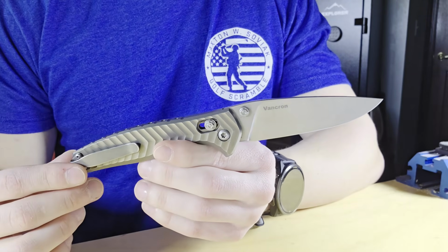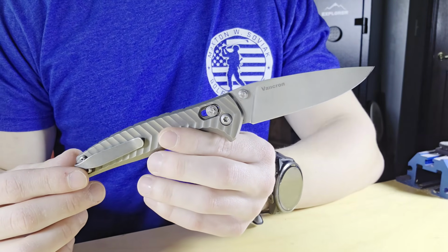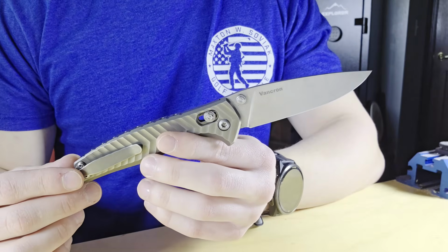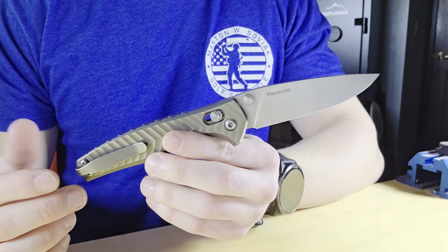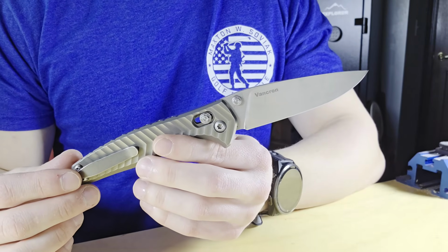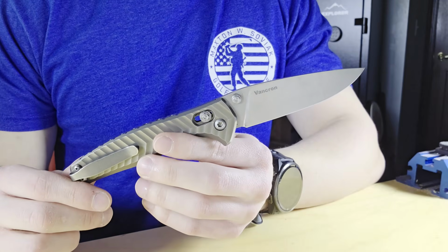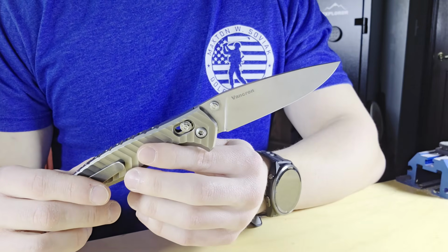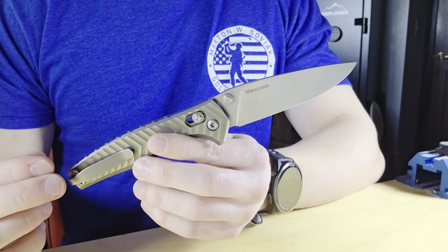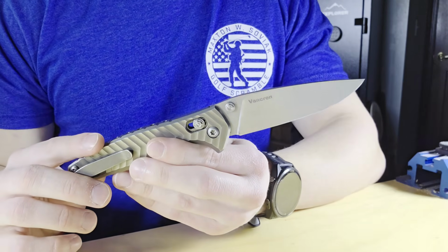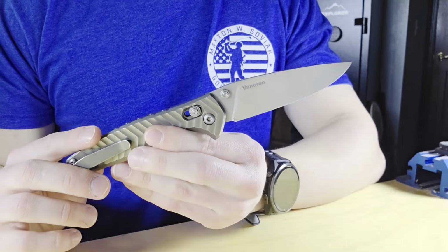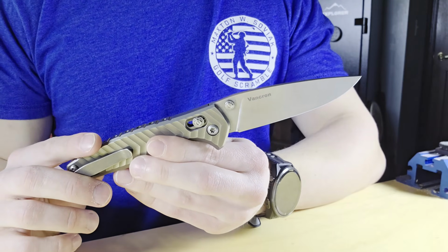Now, with all that being said, if you've watched enough of my edge retention testing in the past, I've described how some of these steels, mainly the high carbide and high hardness ones, self-sharpen to a degree, and they seem to get a little bit sharper before dulling again. And I experienced that in Vancron more than any steel I've ever experienced it in before.